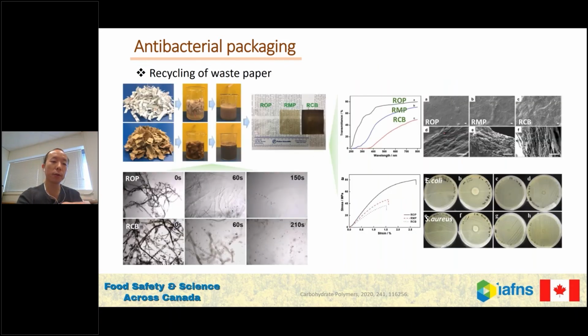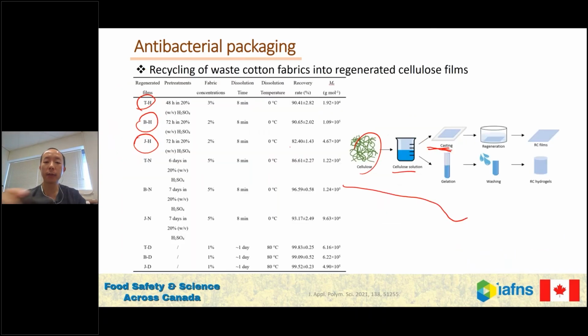We also dissolve waste paper into the solution and get the cellulose films. And after that, it's very easy to load those antibacterial compounds. We can either directly add those compounds in the solution. If they are stable in the alkaline or in the acid, we can directly mix it with the solution. Or if it's not stable in a harsh condition, we can immerse our cellulose film in the antibacterial compound solution.